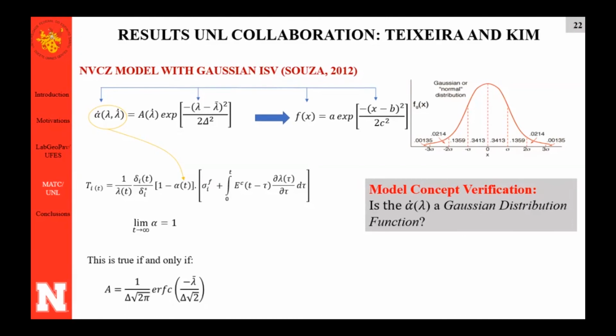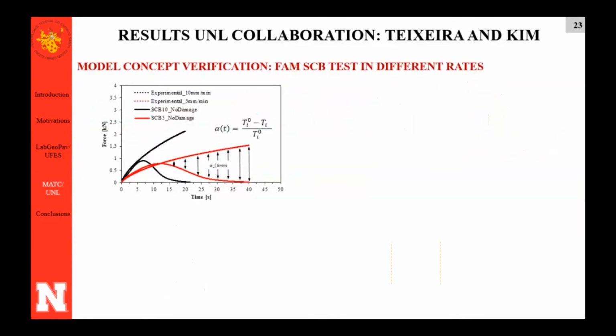To use this model, we need two parameters, this big delta and the lambda bar. But lambda bar is not a value that we need to calibrate. It comes from an experiment, because if you plot the Gaussian function, the lambda bar will be the position of the mean value. So it comes directly from the experiment. Also, the big delta does not need to be calibrated. It's basically the standard deviation of the values throughout the X values. So I tried to verify if this model based on a Gaussian function could work for our asphalt materials prediction.